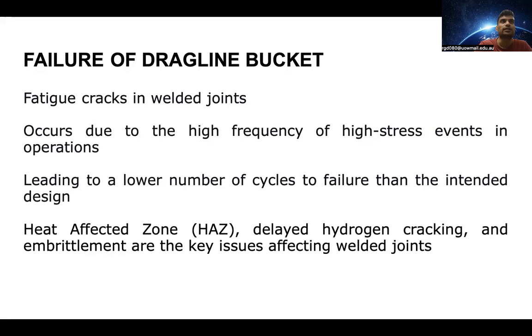The stress is mainly in the welded joints due to the tensile residual stresses acting at the heat affected zone. It can also be due to delayed hydrogen cracking and embrittlement. These are some of the major causes of failures in weld joints, and there could be other reasons as well. Wear could be one more reason, because the metal is quite abrasive, and this causes abrasion of the plate, which could eventually lead to wear and failure of the bucket.